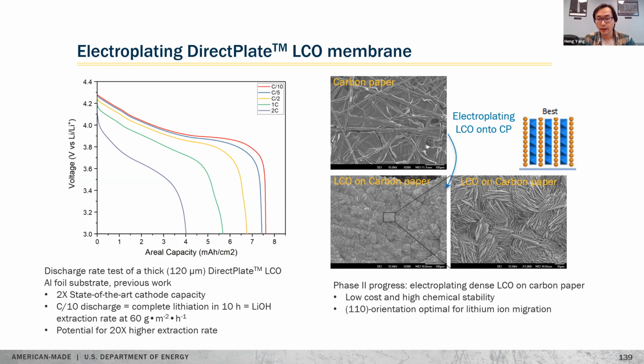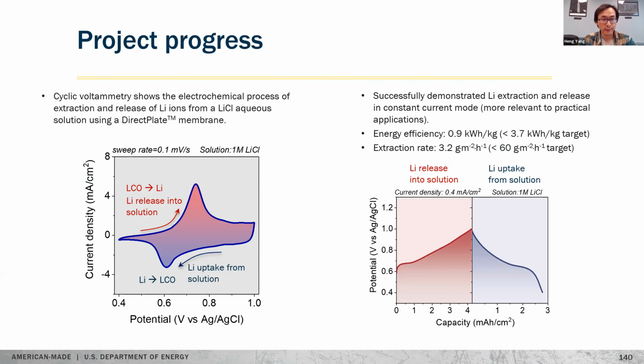So the dense LCO layer formed on carbon paper, the zoom-in view shows its layer structure. This layer structure indicates the diffusion channels are aligned parallel to the lithium extraction direction, which should be optimum for extraction kinetics. Next slide, please.